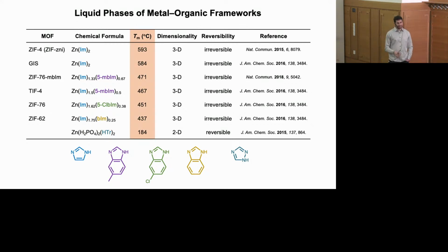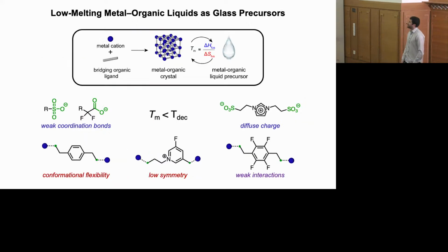Just for reference, there's something on the order of about 80,000 different metal organic frameworks that have been synthesized and structurally characterized. And so this is an incredibly small subset of materials compared to all that is out there. And so my group became really interested in thinking about rational thermodynamic strategies for bringing down the melting temperatures of metal organic frameworks to provide access to a much wider range of materials that can be converted into a liquid that could be then quenched into a glass.